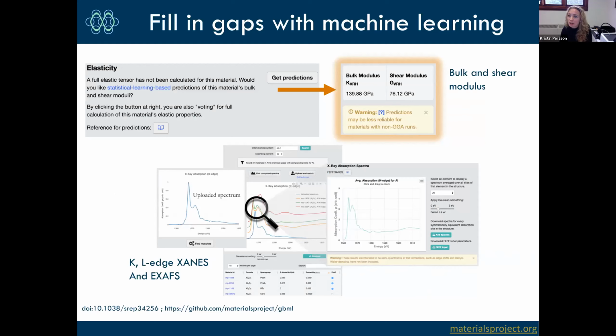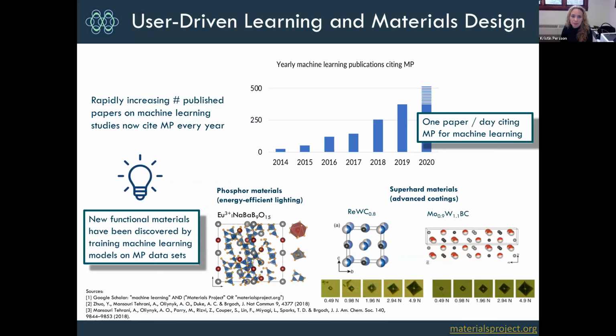We do similarly with our calculated XAFS and XANES, K-edge and L-edge, of which we now have over 500,000 spectra on the Materials Project. You can upload your own spectra, and if you just know that, yes, this is some sample I made that contains aluminum and oxygen, we use machine learning algorithms to correlate the local environments in our crystalline spectra to your measured spectra and give you a ranked list of crystalline materials where we think the local environment looks as similar as possible to what you collected. So again, hoping to accelerate the characterization of novel materials from a local descriptor of the structure.